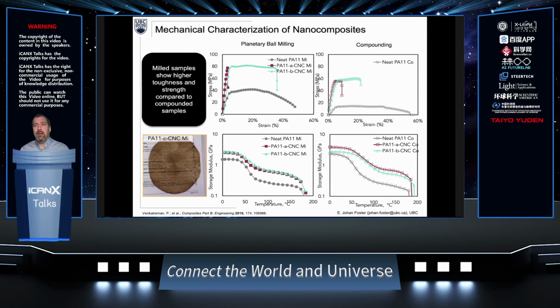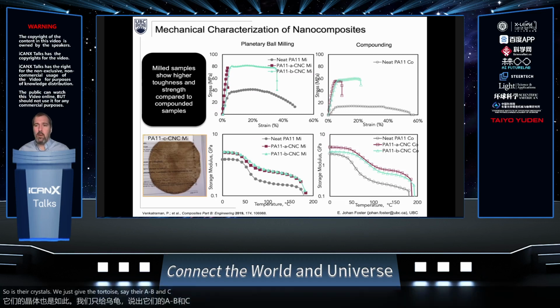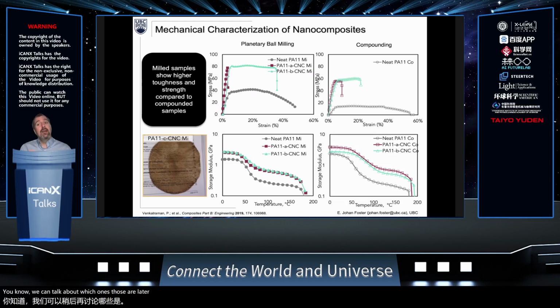I could give a whole talk on the differences between cellulose nanocrystals. So we used three commercially available cellulose nanocrystals. We'll just say they're A, B, and C. We can talk about which ones those are later. But in this case, the ones that were C had a lot more charges on their surface, a lot less thermal stability, and they turn black and don't reinforce very well.